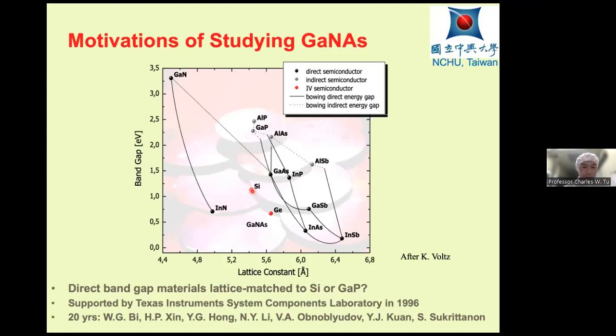And actually we started this work in 1996. And what we found is that instead of the bandgap increasing with increasing nitrogen concentration, as we would get by drawing a linear interpolation, the bandgap actually decreases, and decreases quite rapidly. And so it's a huge bandgap bowing like this.